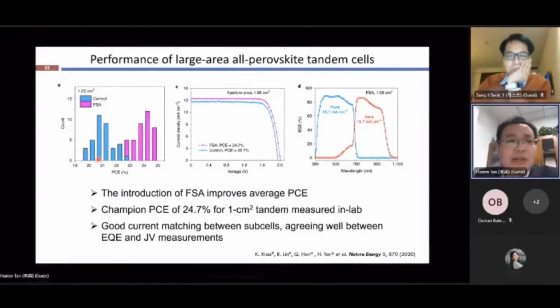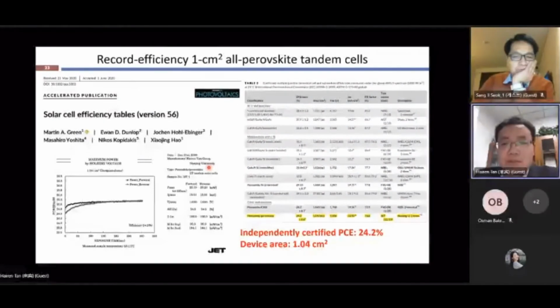As a result, due to the improvement in the hole transport layer for wide band gap perovskite, and also the additive for the narrow band gap perovskite, we can increase the efficiency up to almost 25% from the previous 22.7%. And from the EQE spectra, we can see that the current matching condition for these two subcells is quite reasonably good. We sent one device for certification at JET in Japan, and we got a stabilized certified efficiency of 24.2%. This result has been included in Professor Martin Green's solar cell efficiency tables last year.